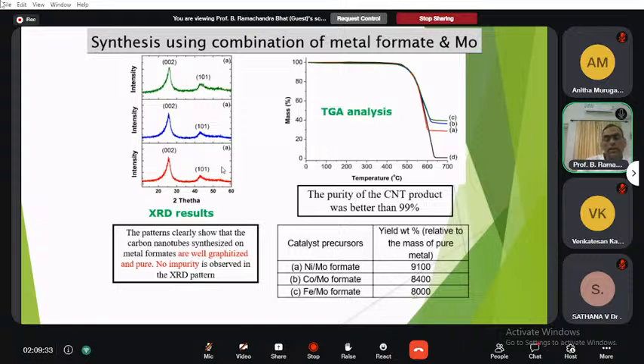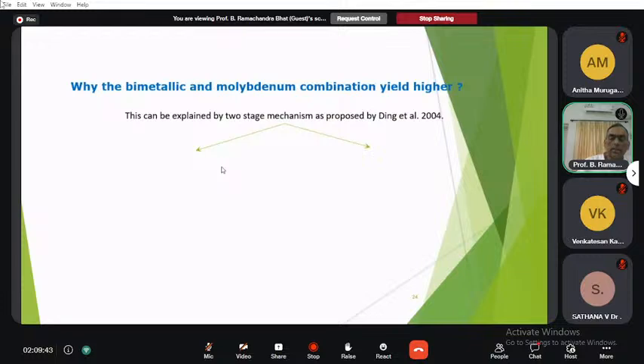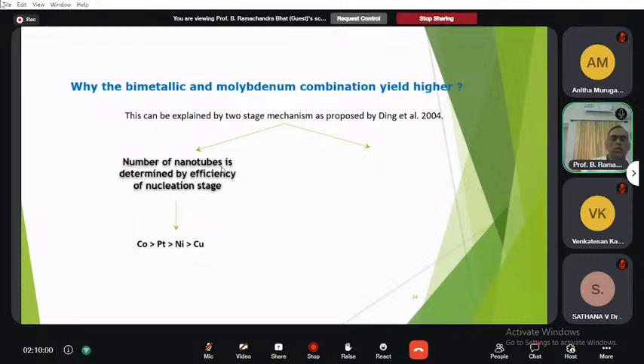You can see that the nickel molybdenum formate, the bimetallic combination, gave around 9,100 weight percent, and that's a very good yield. This bimetallic and molybdenum combination yielded very high carbon nanotube. Now we can analyze this. It is explained in these two mechanisms.